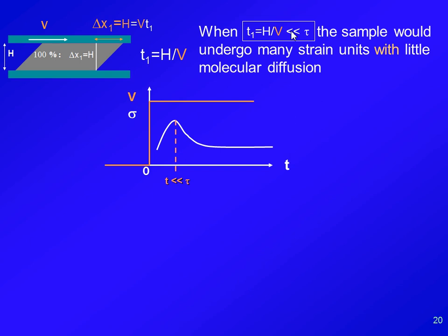Mechanically, it is clear that elastic deformation did not proceed forever, because that would imply your force would monotonically grow. So instead, you find it stopped growing and started to decline, at a time scale still very short compared to what molecular diffusion would allow you to visualize the dynamics. So it's clear, mechanically speaking, that you have elastic deformation.